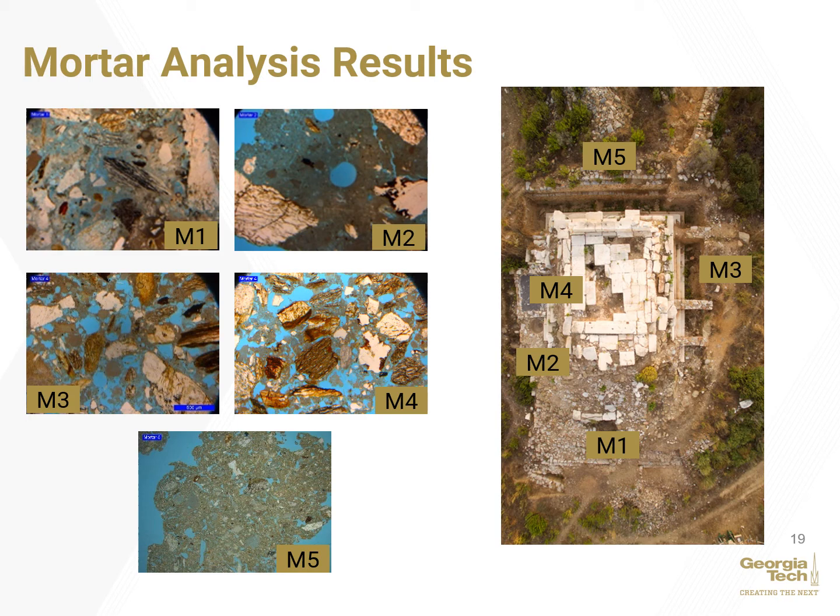And finally, sample M5, which is from the back retaining wall, contains a larger volume of very fine-grained sand, including mica, quartz, calcite, and that was dispersed through the paste as compared to other samples. And the paste in sample M5 is brown in color, extremely soft and porous, indicating that the lime amount is relatively lower.